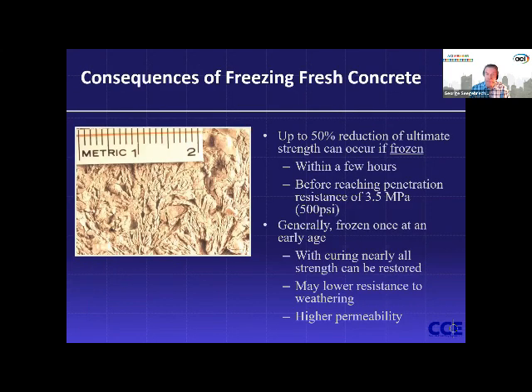So avoid the freezing for the cold weather, because it can reduce the properties and strength of your concrete by 50%. But that's just in the frozen zone. If you catch this early, you have kind of two thermoclines fighting each other. You have the cold from the top working its way into the body, and you have hopefully still the heat of hydration resisting that. So how far the freezing goes is important before you decide what you're going to do to react to that.